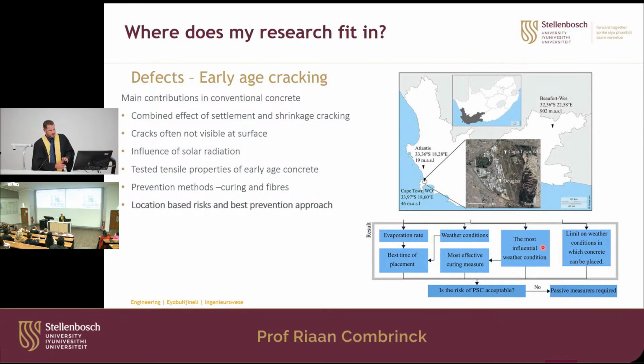Okay, then also location risk-based analysis. We looked at what is the best approach to reduce these cracks if you're casting in Cape Town versus Beaufort West. We took hourly data, and statistically you find what the evaporation rate is at a certain time of day, and also based on the seasons. Based on that, you can say what is the best time to place your concrete, and you can also look at what the most influential weather conditions are. For example, in Beaufort West, it's more temperature, so you must maybe not cast in the middle of the day when the temperature is hot, but maybe later in the day. And in the Cape, it's more wind, so there, using windbreaks is more effective at reducing the cracks.